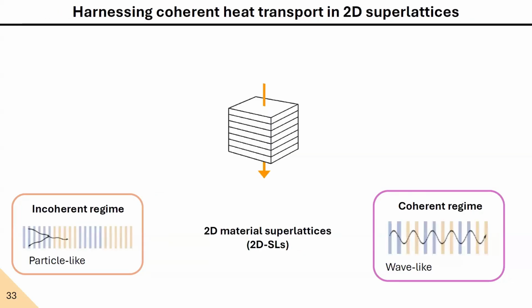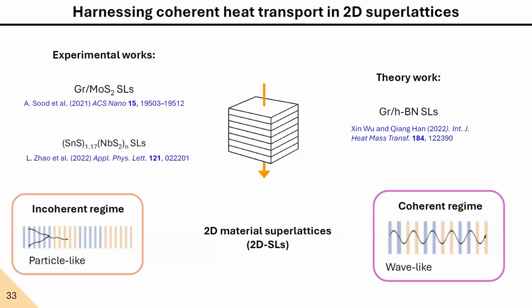So how could we harness coherent phonon heat using 2D materials? Well, we could make 2D material superlattices. So we can stack two different 2D materials in a periodic fashion, and therefore we should be able to observe the same effects. However, this is challenging. The fabrication of these samples is not straightforward, and there are only two experimental works which studied the possibility of coherent heat transport in two-dimensional superlattices. However, none of these works provided a clear evidence of coherent transport at the nanoscale.